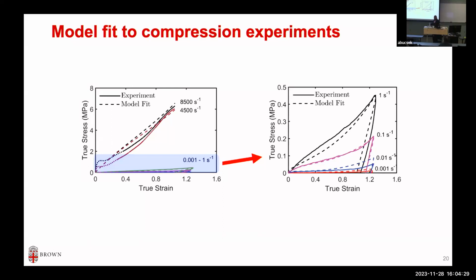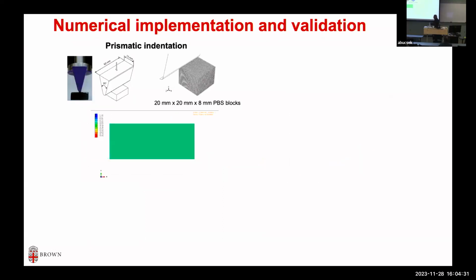We calibrated it. The question is, of course, we use the data to calibrate it. So that matching is by design, not by nature, right? So how do we really know the model has the predictive capability that we can trust, especially for complex geometry when we are designing these sensors, tissues, or energy absorbing devices? So what we did was independent experiments. And that's one of the reasons we do a lot of experimental work. So we test the model's 3D capabilities. Our model has been calibrated on 1D data. Don't touch the calibration. We did independent experiments.